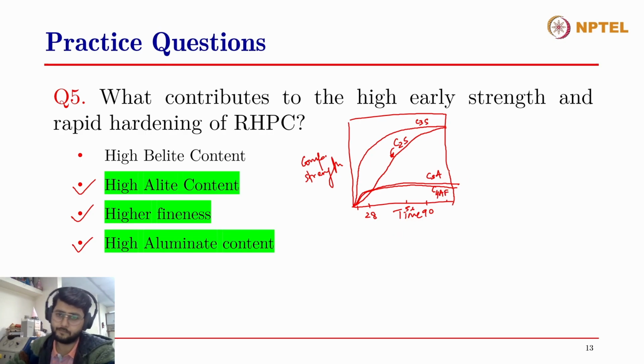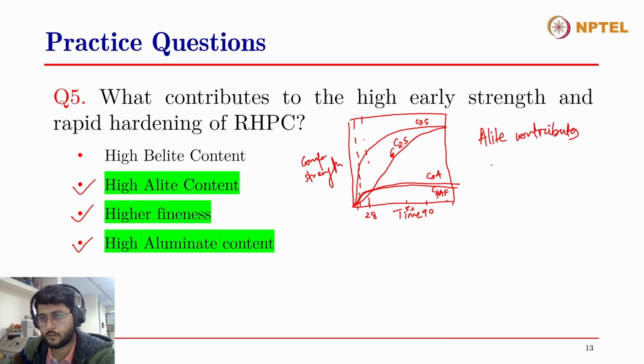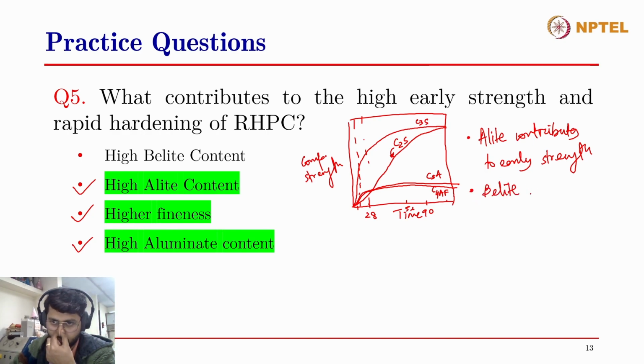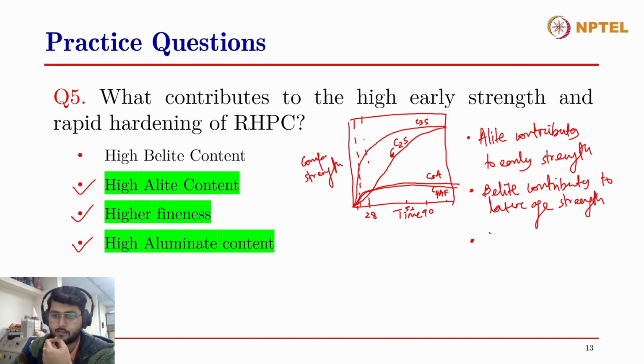So you can see that at around 28 days, or in the case of early strength, the only factor that contributes to early strength is alite. alite contributes to early strength. On the other hand, belite contributes to later age strength, while aluminate does not contribute much to the strength.